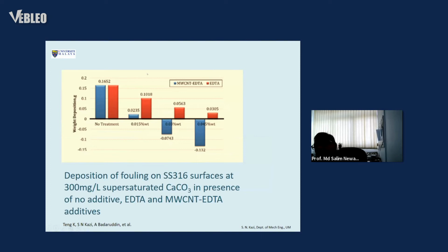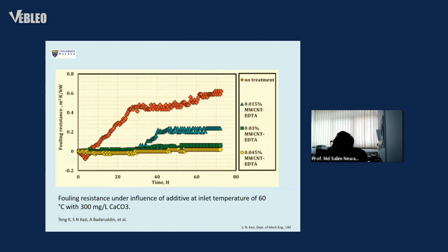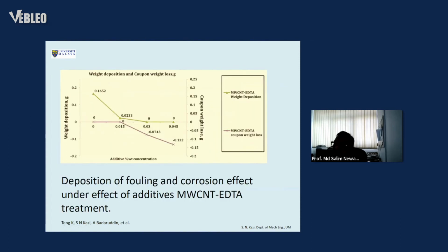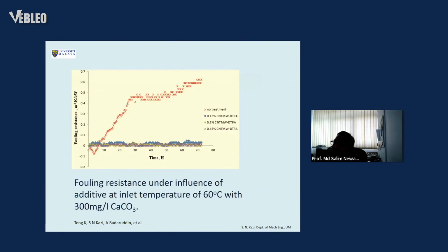But if the multi-wall carbon nanotube structure is added in this experimental case, we find it also reduces the deposition, but it's highly corrosive. That is why we have to find some other fluid. If it is DTPA functionalized nanoparticles of the same multi-wall carbon nanotubes, then the fouling deposition is reduced, and the equipment surface is not damaged. So that study enhanced our research in that specific field, where we get a higher percentage of retardation, and the heat exchanger surface is not affected much.